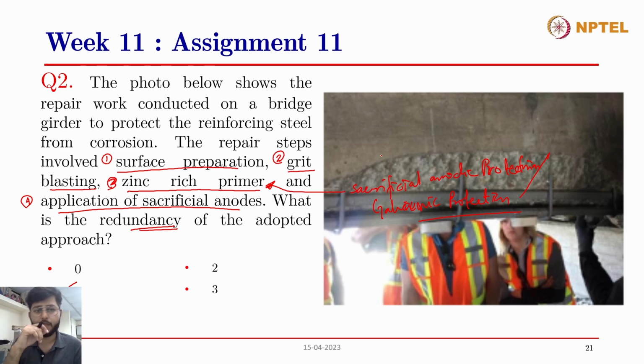And further, at the end, they have applied sacrificial anodes, and these sacrificial anodes are typically zinc anodes, and they are also a similar kind of system. The only difference between a zinc rich primer and a sacrificial anode is that the sacrificial anode is dynamic in nature. It can provide a current as per the demand of the concrete with the due course of time, as the corrosion proceeds in the zinc and the current demand in the concrete fluctuates.